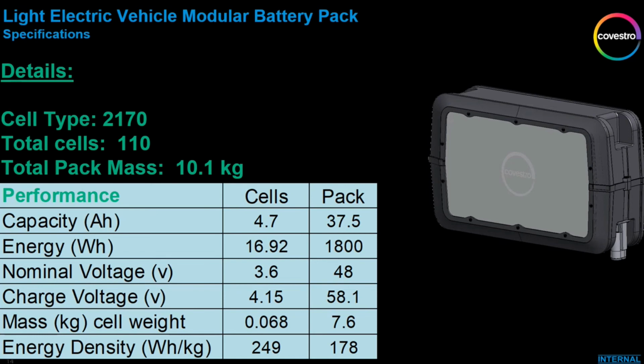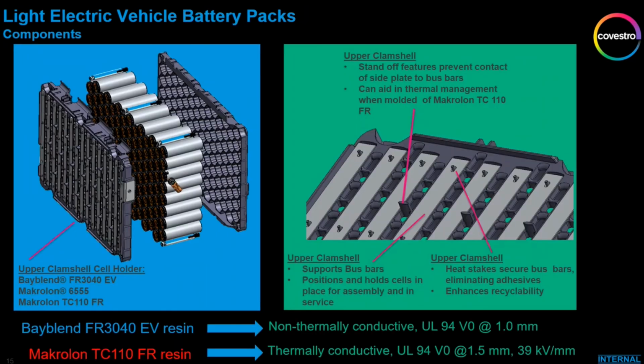So the pack that we developed has pretty common specifications for these applications. We chose the 2170 style cells. We put 110 of them in the pack, which gives us a total mass of about 10.1 kilograms. You can see the performance specs. That's about 1,800 watt hours of energy in the pack. Very common size for these types of two-wheeler packs. And then finally, we get down to the critical component, energy density. So we're talking about 178 watt hours per kilogram, which when you look at these types of packs is pretty good performance for these packs.